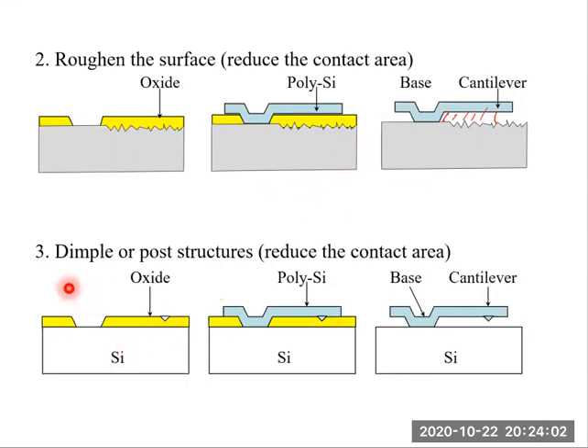Similarly, we can use a dimple or post structures to avoid stiction. As shown in this figure, we can make a dimple on this outside sacrificial layer by partial etching. Then we deposit and pattern the polysilicon structural layer and release the cantilever by sacrificial etching. So during the drying process, this cantilever will be pulled down. Okay, they will adhere to the substrate during drying, but after it's completely dry, this cantilever can bounce back, right? Because of the reduced contact area due to this post structure.